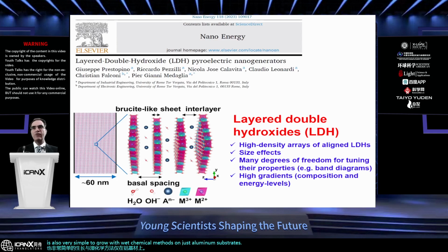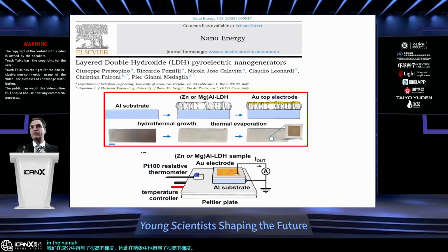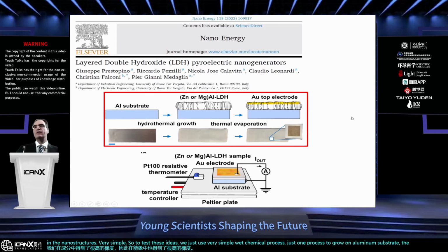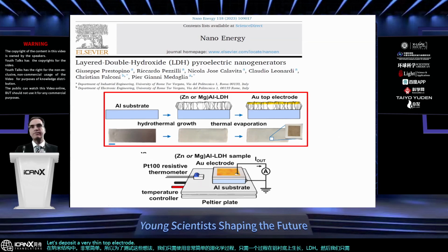So if we use that approach that we consider in that paper, there is another advantage: we get high gradients in the composition and, therefore, in the energy levels in the nanostructures. Very simple. So to test these ideas, we just use a very simple wet chemical process, just one process to grow the LDH on an aluminum substrate, and then we just deposit a very thin top electrode metal. And then we test it as a pyroelectric nanogenerator.